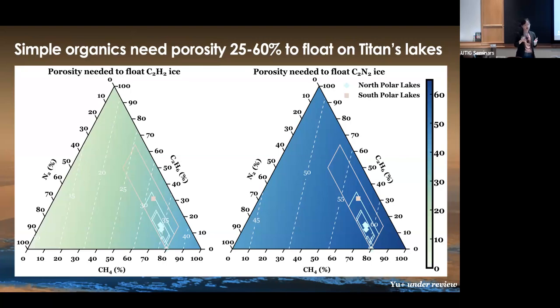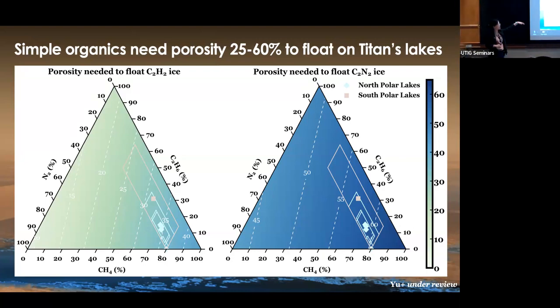And it's not like Titan's lakes cover the whole ternary diagram. Actually, we do have measured composition of the lake. Okay, all the possible compositions. The lakes actually only occupy these small areas shown in these diamond boxes. These are the measured compositions of the lakes. On this diagram we showed contour plots, and these contours show you the porosity that is needed to make things float at certain compositions, if that makes sense.